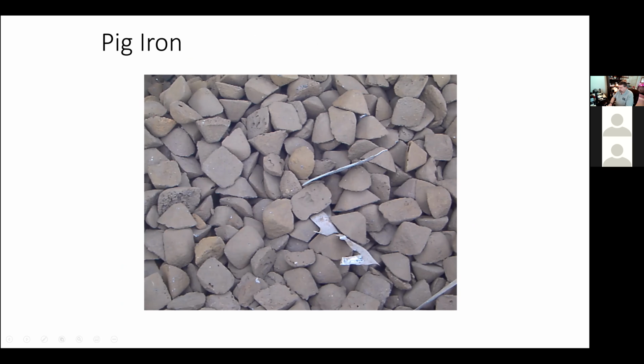So this is pig iron that's being produced by the integrated route, usually in a blast furnace or in what we call a mini blast furnace, which is similar to the blast furnace, but it operates with charcoal instead of coke. And sometimes they'll pig this material and they'll use this as a charge material for the electric arc furnace. And again, this typically contains 4.3 to 4.5% carbon, anywhere from 0.1 to 1.1% silicon, maybe 0.3 to 0.5% manganese. But other than that, it has very, very low copper, nickel, moly, and tin content.